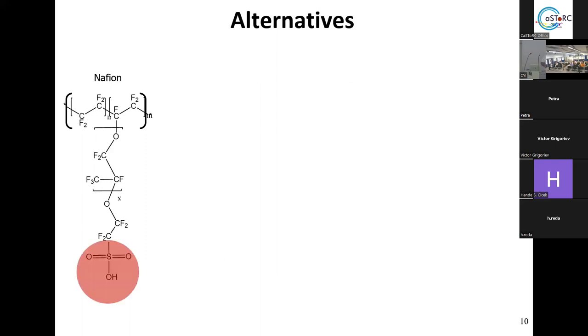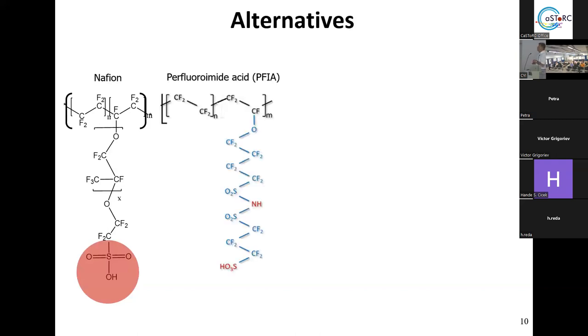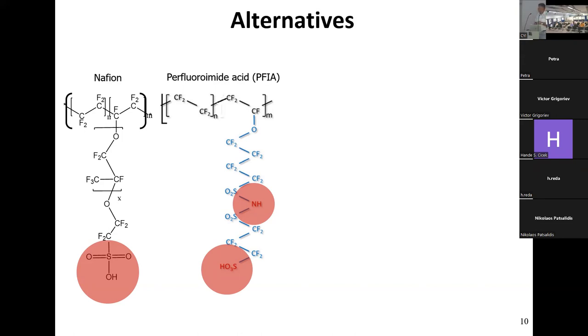One alternative is multi-acidic membranes with more than one ionizable group per monomer, such as PFIA — perfluoroimide acid — which has two groups: a sulfamate at the end and a sulfonylimide in the middle, both ionizable. An important parameter is lambda, the hydration level — the number of water molecules per ionizable group. Lambda zero is dry Nafion; lambda five means five waters per group. Typically experiments vary lambda from zero to twenty.